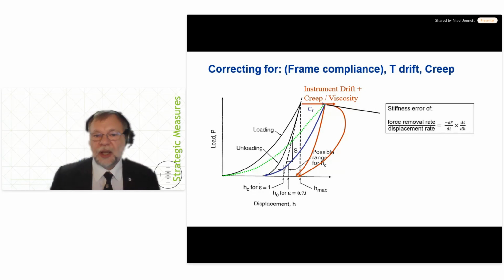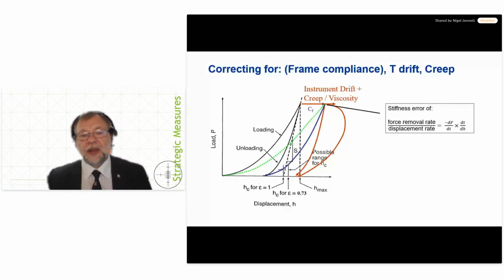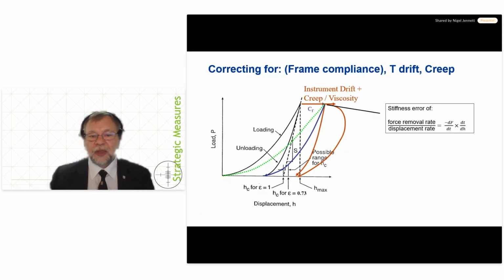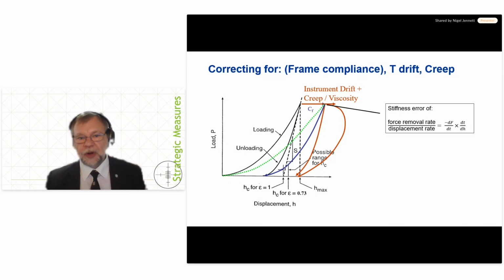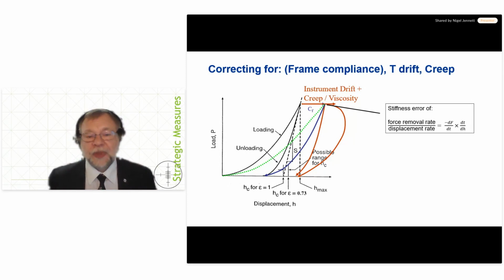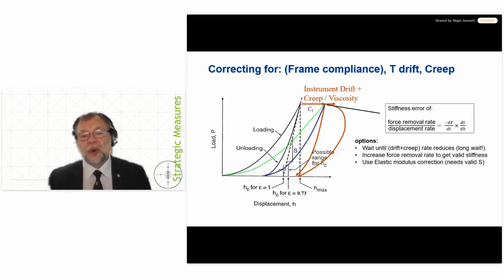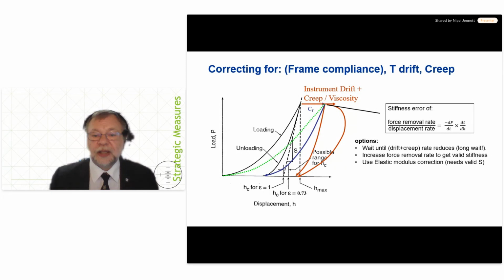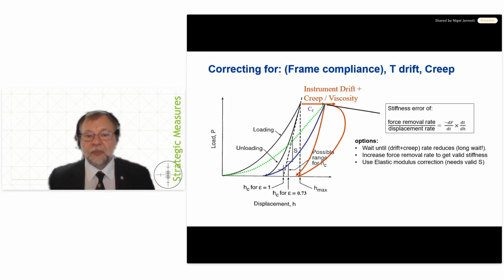And in those circumstances, you end up with a stiffness error. And that can actually give you a negative stiffness and therefore an apparently negative elastic modulus. But unfortunately, you won't get a Nobel Prize. It is just an error. So the question is, what do you do about that? Well, the standard says quite simply that you wait until the drift rate is low enough or the creep rate is low enough, and then you can unload. And low enough means that you have the option of increasing the force removal rate so that you beat the creep rate and then get a valid stiffness measurement.